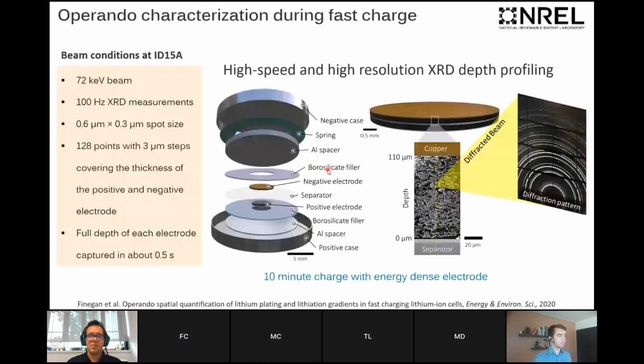And we designed this experiment where we made a coin cell with small electrode pucks of about 4 millimeters in diameter. These were thick electrodes, about 100 to 110 micrometers thick. So they were high energy density electrodes. And we designed this cell such that it was favorable for high speed and high resolution X-ray diffraction. This work was conducted at the ESRF on ID15A. And we used a beam with a spot size of less than a micrometer, and we conducted step measurements of XRD from the copper current collector to the aluminium current collector, so through both electrodes, with a step size of about 3 micrometers. So stepping down, as you can see on these yellow dots, from current collector to current collector.